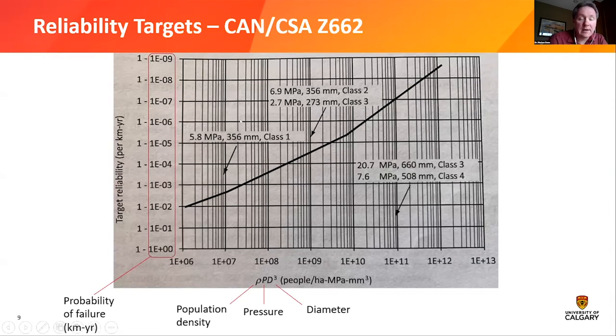All right, reliability targets. So this is an example from the Canadian pipeline code on what a reliability for a pipeline system looks like. And this is almost a surrogate for risk analysis, because on the horizontal axis, we have three variables that go into this product. We have the population density as a measure for the consequences, or how many people would be affected if there would be a pipeline failure. And then we have pressure and diameter of the pipeline. Bigger pipelines usually cause larger consequences when they fail.